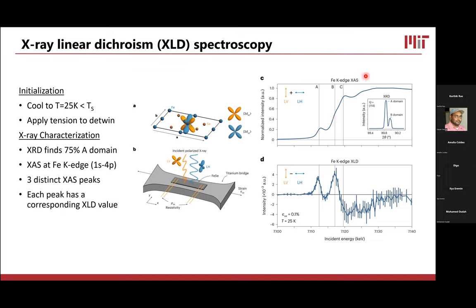But you can see that there are two distinct peaks around this feature B, and B itself has a small little bump here. So these peaks are pretty well understood in the literature. If you go to our paper, you can find the citations for it. But they give us extra evidence about the local nature of the iron atom. Because this is an iron K edge absorption, you can think about this as an individual X-ray interacting with an individual iron atom. So it gives you a way to probe the local environment of that iron atom. This B feature is the normal edge. The C feature comes from extra scattering of electrons in the vicinity of the iron atom, and it becomes sensitive to the lattice distortion around the iron atom.